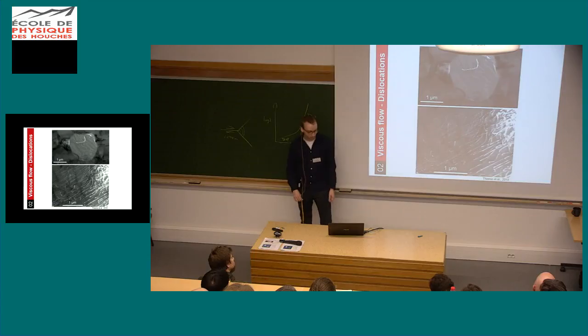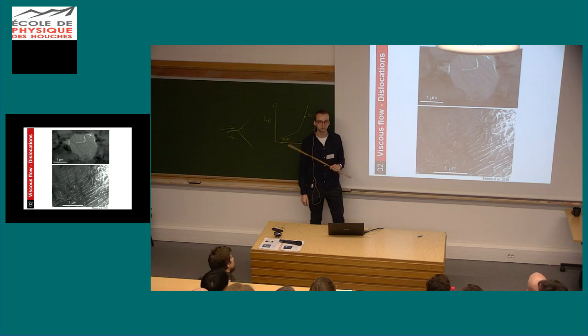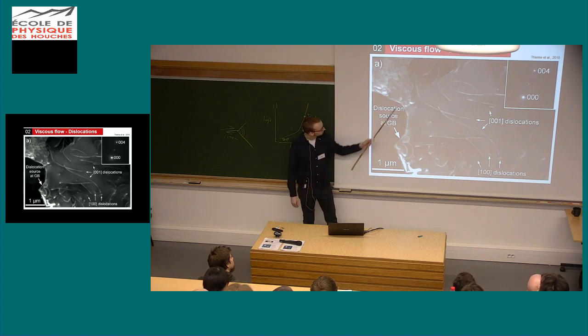For even higher resolution, you can use the TEM. Two TEM images here nicely show the heterogeneity in grain size I was speaking about. On the top, you have a small grain with just one single dislocation. On the bottom, you see a bigger grain which is virtually full of dislocations — about 7 times 10 to the 13 per square meter, a very high concentration. We also see dislocations gliding into perpendicular slip systems in the [001] and [100] directions, and a little bit more unusually, sometimes grain boundaries acting as dislocation sources — in one case a source with very low activity of just three loops.